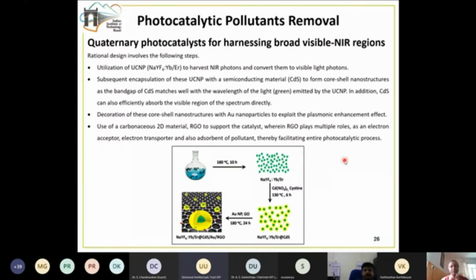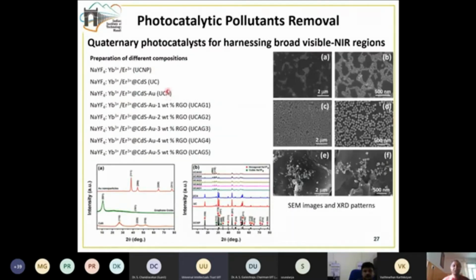So we prepared this quaternary photocatalyst, which consists of the upconversion nanomaterial, then the upconversion nanomaterial with the shell of cadmium sulfide, then decorated with these gold nanoparticles, which are these red dots here, and the entire thing is supported on the reduced graphene oxide. So we prepared this quaternary material. And then we prepared this material in different compositions to prepare a nanocomposite with 1 weight % RGO to 5 weight % RGO. And similar to the previous work, we wanted to see whether our synthesis is successful and what type of morphology is being formed in this material.